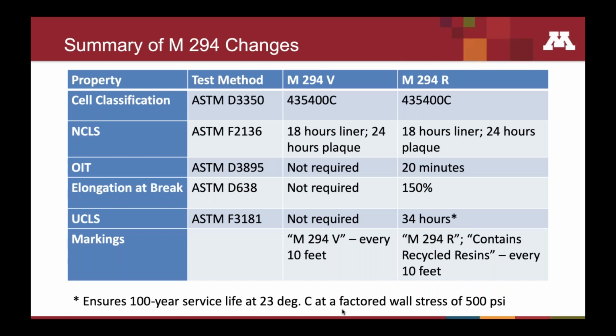So now the current M294 standard allows either virgin or recycled materials to be used. The cell classification, which identifies the material properties, are identical for both pipes, M294V and M294R. The NCLS, which is the notched constant ligament stress requirements, are identical for the two pipes. For the pipes manufactured with recycled materials, we require an OIT test, which is an oxidation induction time test, which ensures that those stage 3 chemical failures do not occur. And then we also require an elongation at break test for the M294R pipes, as well as that UCLS test that I mentioned of 34 hours. And then we finally require that for virgin pipes, it's marked as M294V, and for recycled pipes, it's marked as M294R. And that 34-hour test is designed to ensure that those pipes manufactured with recycled materials will last in excess of 100 years at a factored wall stress of 500 psi.